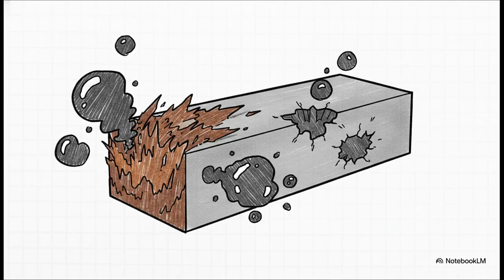And it's not just caustic soda we have to worry about here. Even invisible, naturally dissolved gases carry their own quiet stress. Dissolved oxygen in the feed water will directly attack the iron to produce rust. Dissolved carbon dioxide reacts with the water to form carbonic acid, which drops the pH and leads to acidic corrosion, leaving these rough, pitted scars across the metal surface. If left unchecked, these incredibly quiet chemical reactions will easily eat right through the strongest steel.